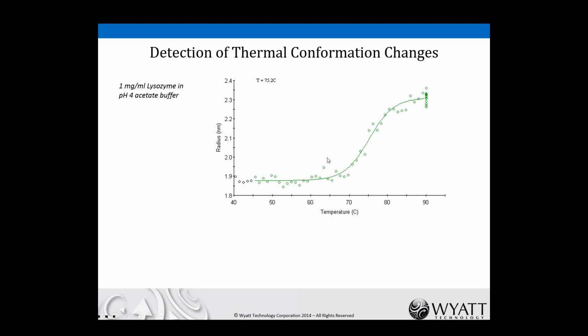So lysozyme, under many conditions, is pretty nice, and actually you can unfold it and refold it multiple times without any aggregation going on. And so what you see here is a temperature scan, and here's the radius of the molecule. As we go through the temperature over here, we can see it increase a little bit, from 1.9 to about 2.3 nanometers.